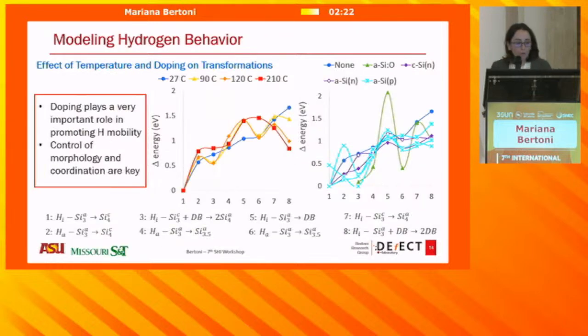One quick thing that I want to note is that we have done a whole lot of modeling. So 1 to 8 are all these transformations that I mentioned before. We've done the same calculations for different temperatures and different doping. And all I want to say here, because I don't have a lot of time, is that doping plays a very important role in promoting the hydrogen mobility. So you can see how the energy dramatically changes if you have amorphous silicon oxide, or if you have just a pure amorphous silicon N or P type. And the other thing that I do want to mention is how important the control of morphology and coordination of neighboring atoms in your amorphous silicon is.